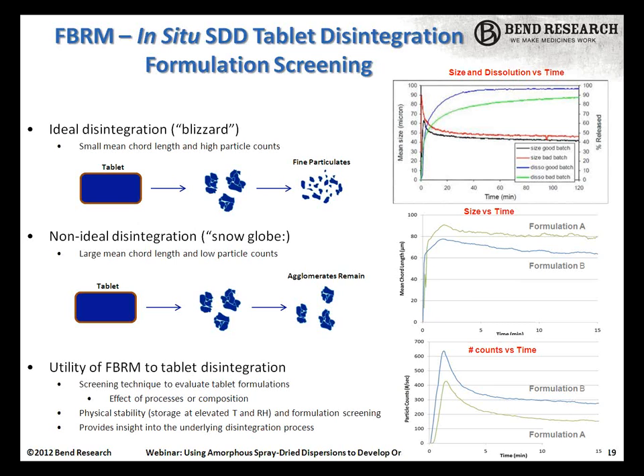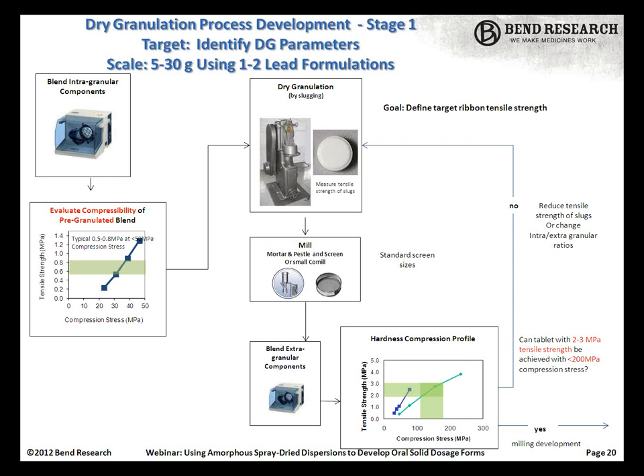So once we've selected a formulation, then we move into the process development. So once we've identified a lead composition, we still stay at this small scale for the very early prototyping. And here, though, we're looking at the compressibility and identifying the solid fraction and the particle size that might be targets for when we scale to the roller compaction.